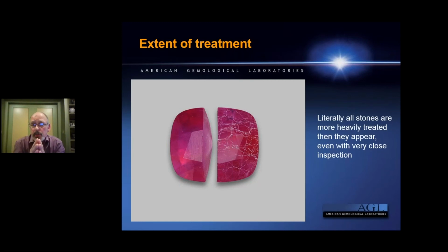And this surprised me, because what happened, you see the whole surface is traversed by fissures. The difference is these are very fine fissures, so these are even more difficult to detect. The inclusion features that I was showing you, the flash effect, the gas bubbles, these are when you have larger volumes of this glass. With very, very fine fissures, it's much more difficult to recognize this. So this is a clear demonstration that all of these stones, regardless of how much you think they might be, are all more heavily treated than you realize.